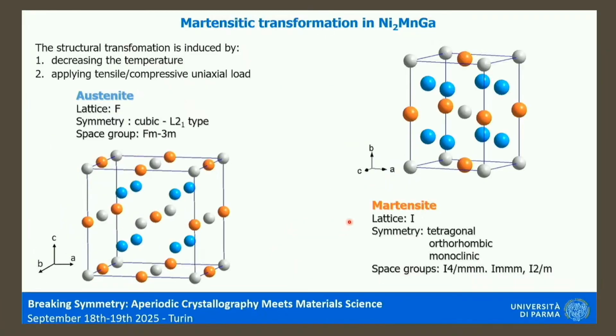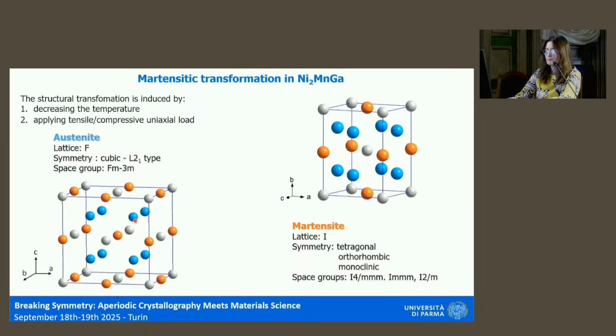At the base of the physical properties of Heusler alloys, there is the Martensite transition. The Martensite transition is the solid-state transition from the parent phase, showing a cubic symmetry. It's the classical austenite. This is the classical name in metallurgy. And by going down with the temperature, we can observe the Martensite transition. The martensite is characterized by a lower symmetry. This is the basic lattice. And so the symmetry can be tetragonal, orthorhombic, or eventually monoclinic.